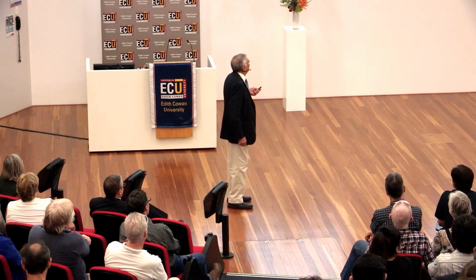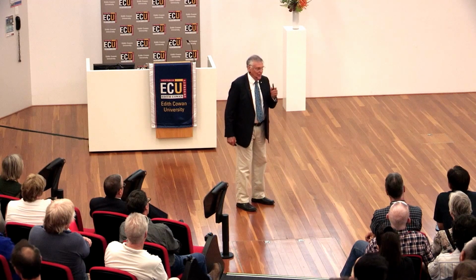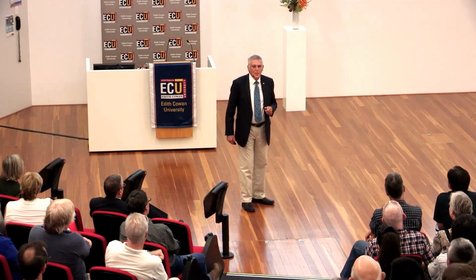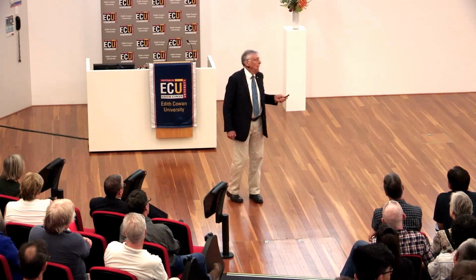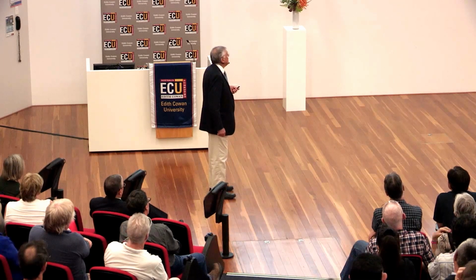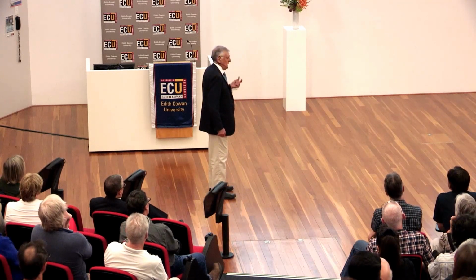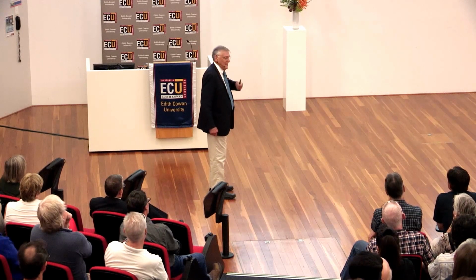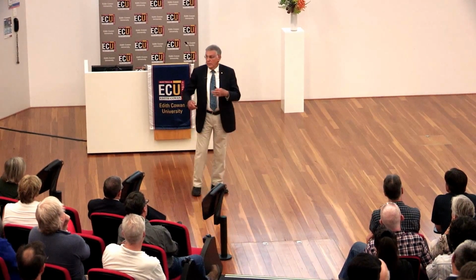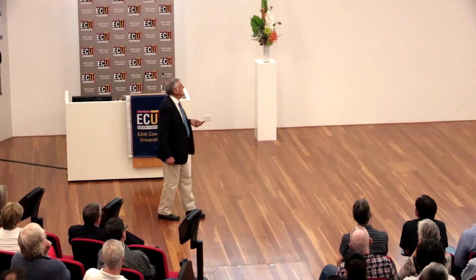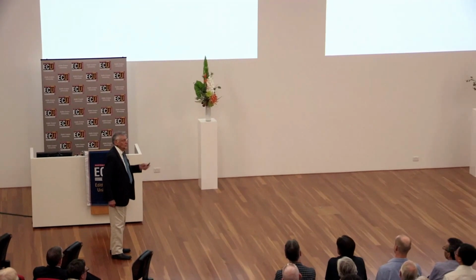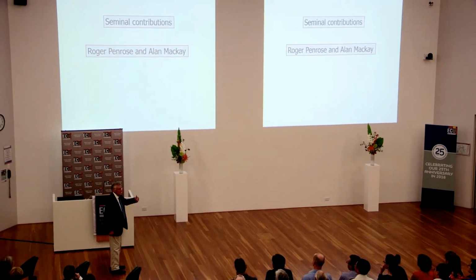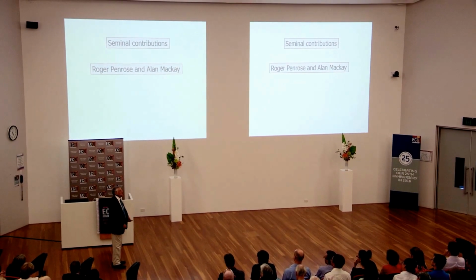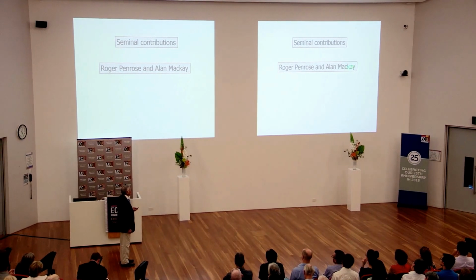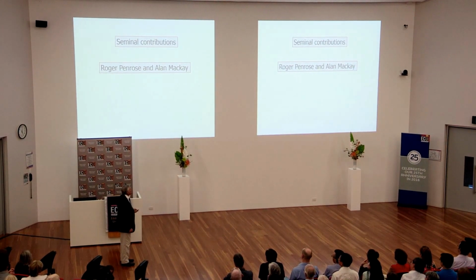Anyway, I want to summarize by doing a few things. Number one, I want to mention a few people who made seminal contributions. Roger Penrose and Alan Mackay. Roger Penrose, who designed a five-fold quasi-periodic array by Penrose tiles. Alan Mackay, who showed that if you take a diffraction pattern from that, or if you do a Fourier transform of that, you'll have sharp diffraction patterns in the reciprocal space with five-fold rotational symmetry.